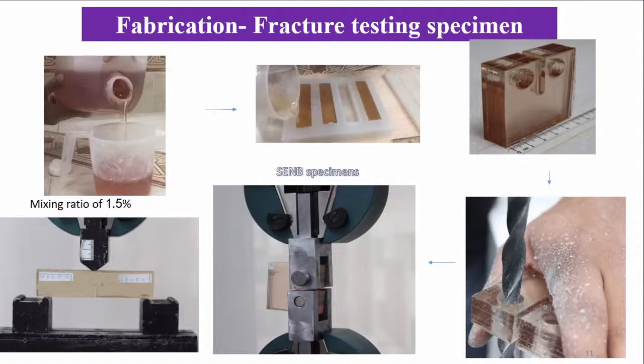Besides, when we were cutting the tip of the notch to make sure we had a more convenient result, we may have introduced a little bit of a plastic region at the tip of the notch. The effect might be different from the SENB specimen to the CT specimen, and that might be another reason. These are the two main reasons that came to our understanding.